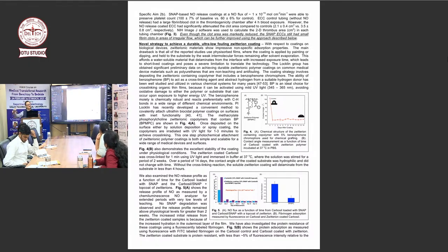The contact angle remains low for so long. And then we say that after we put zwitterion on the NO surface, the nitric oxide release is not compromised. We can still release a similar amount of nitric oxide. One is with zwitterion, one is only nitric oxide, right?